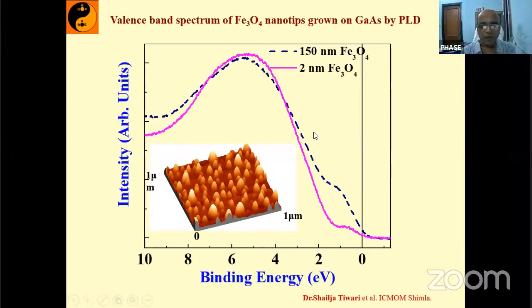This is one of the examples I am giving you, the valence band spectroscopy. For example, I have two types of sample. One is basically a thick film of 150 nanometer of Fe3O4, and another is a nanostructure of Fe3O4. This is our nanostructure AFM photograph. You will see that a very minute change is there in the valence band, but that will change the physics of the Fe3O4 material. That is basically the beauty of this technique and this beamline, that you can have a very small amount of sample, still you are getting a very good quality spectrum without noise.